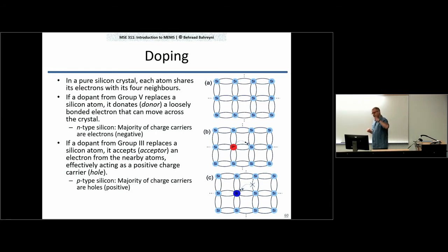Now, because the charge carrier that we have here is a positive charge carrier, we call boron a p-type dopant. So in the first case, we had phosphorus, which when it ionized, you had a positive charge. I think I may have said a negative charge, but you have a positive ion there, and it donates an electron to the lattice. Notice that you still have charge neutrality, right? So the electron and the positive charge cancel each other when you integrate over the entire volume. In the second case, you have boron, which grabs onto one of the electrons from the lattice and becomes negatively charged itself. It is fixed in its place, but the empty spot for the electron can move about. We call that a hole.